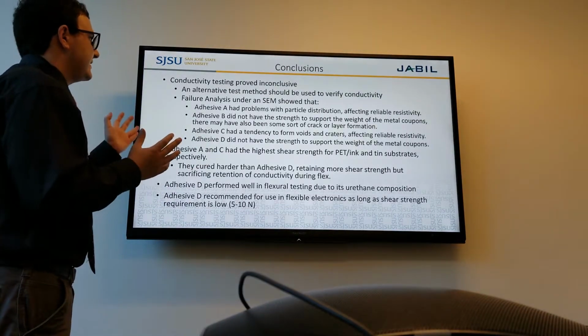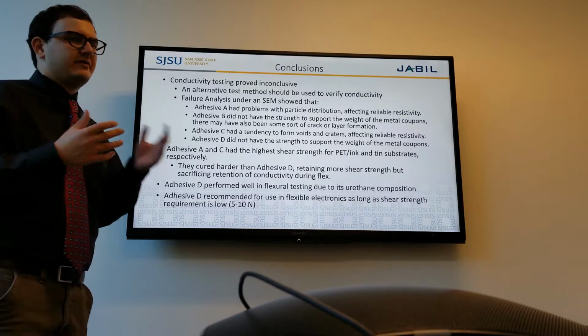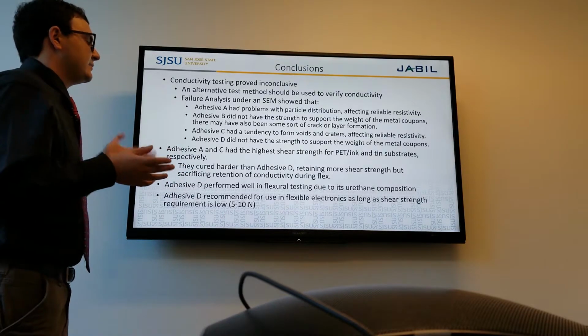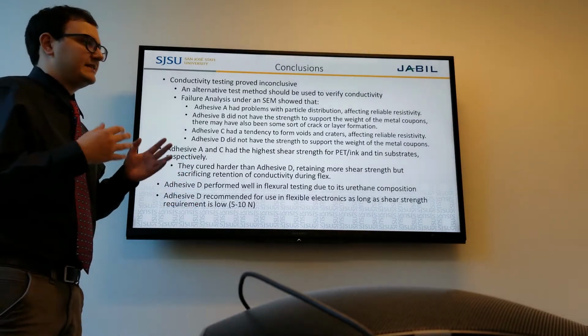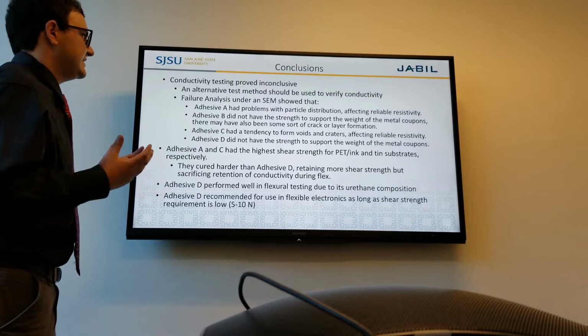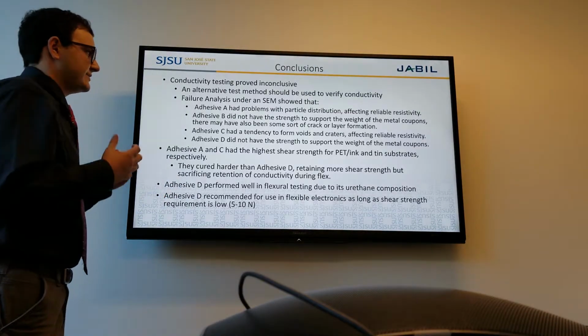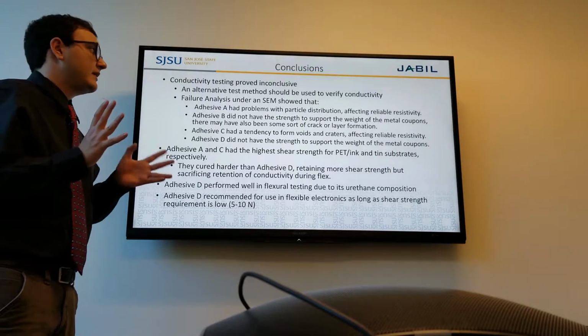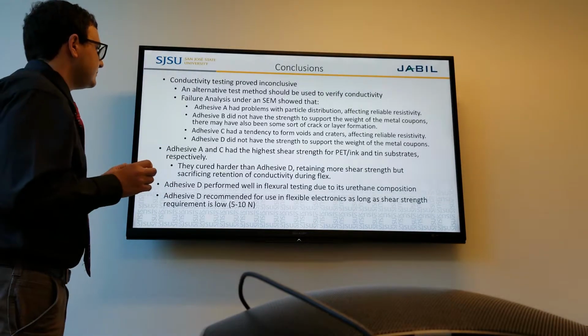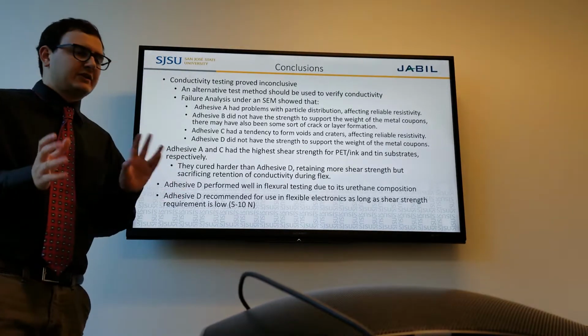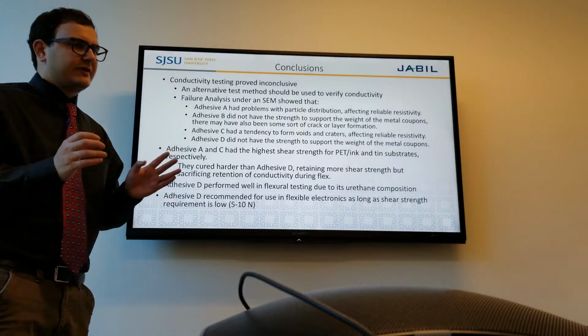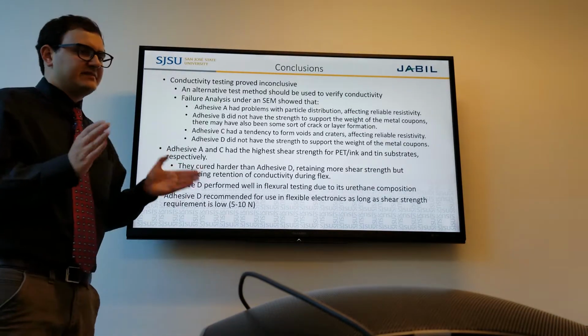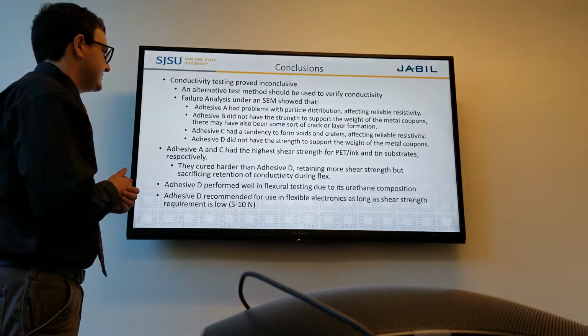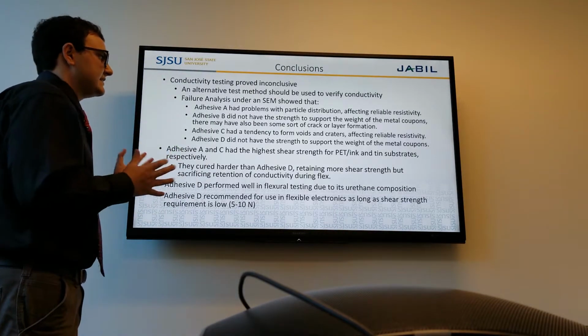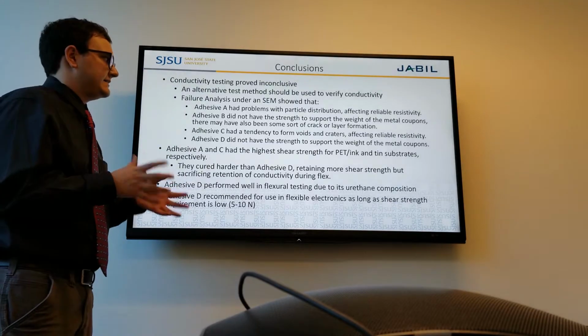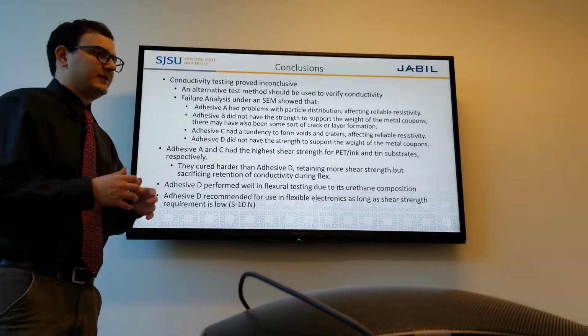When we performed failure analysis under a SEM, we found problems that were not visible to the naked eye. With Adhesive A, we had problems with particle distribution, which affected reliability. With Adhesive B, it just didn't have the strength, and there may have been some sort of crack or layer formation. Adhesive C had a tendency to form voids and craters, just areas where there was no filler of conductive material, and that would then cause a spike in resistivity. And Adhesive D had so much silver on it that it did not have the strength to support the weight of the metal coupons.